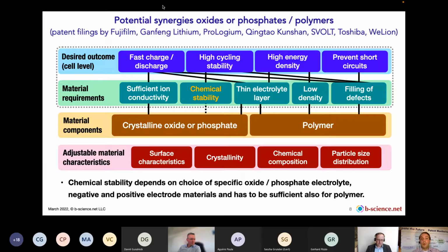And then polymers usually have lower density than the oxide. So you overall have a lower density, which helps for energy density. And finally, polymer can often fill defects, holes, cracks in between inorganic particles. So after identifying the key materials classes, we try to inspire innovation and inventions with these kinds of visualizations, because you then, of course, still have to adjust many materials characteristics, and the invention lies in the experiment in batteries in general, because it's still hard to predict results.